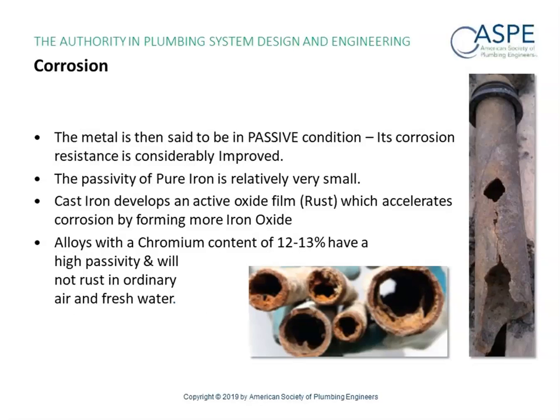What we're looking at here is cast iron. The passivity of cast iron is relatively small. It does develop an oxide film, which is rust, but unfortunately that accelerates corrosion by forming more iron oxide, which is being extracted from the pipe. So what you're looking for is an alloy with a chromium content of 12 to 13% or more. These are highly passivated and will not rust in ordinary air and fresh water. Go ahead and advance.